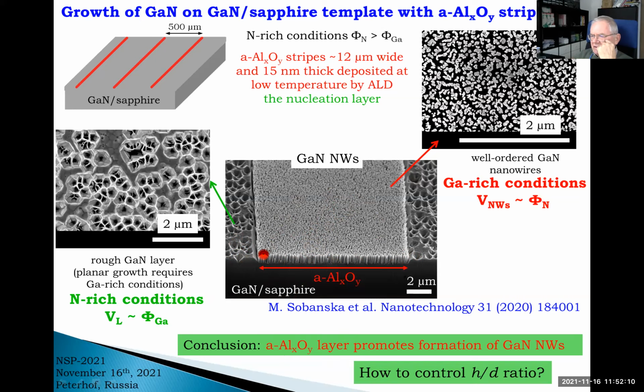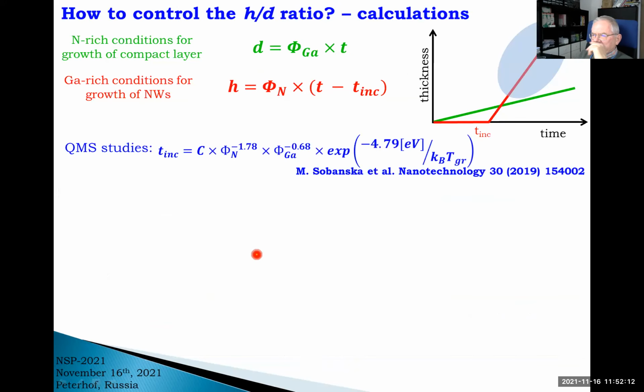So the question is how to control the ratio between them. And the answer is simple. We just assume that the thickness of the compact layer is proportional to the gallium flux. So thickness changes according to this green line. At this moment, this assumption, I will come back to this later, we assume that nanowires grow under locally